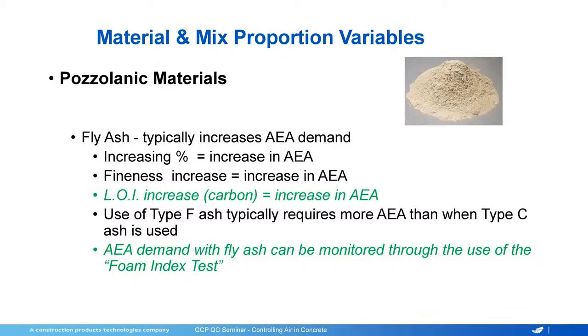We also see treated ashes, and some of them are double treated. What I mean by that is some of them have activated carbon added for mercury abatement, and then a surfactant is added on top of that to offset that activated carbon. And we also see some of the fly ashes that just in general have carbon, high carbon. Those are also treated with a surfactant to make it easier to get air. My personal opinion is I would rather deal with a high carbon and increase my dosage of air entrainment than have it treated. That's just my opinion.